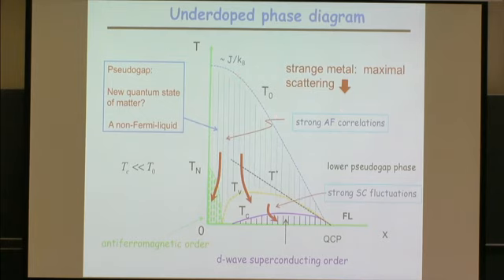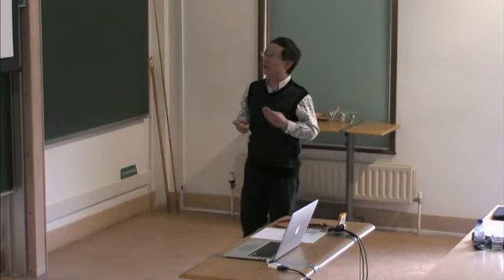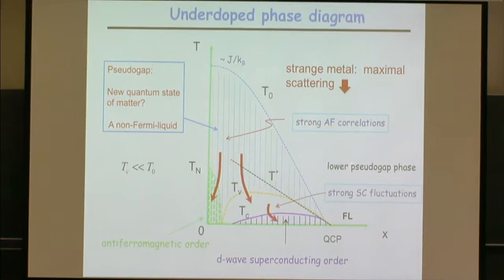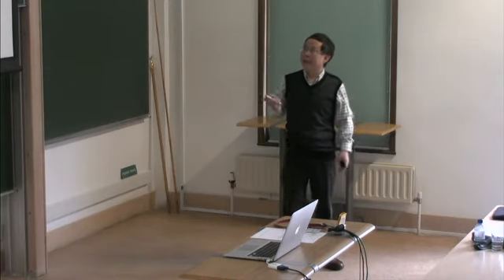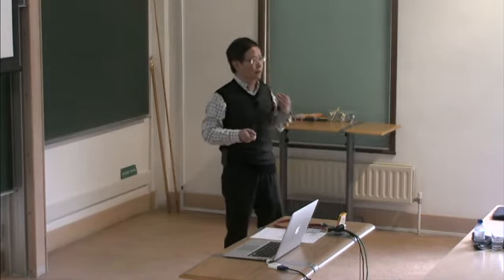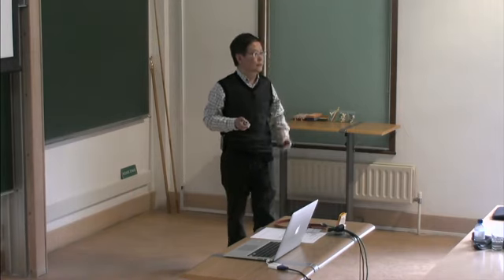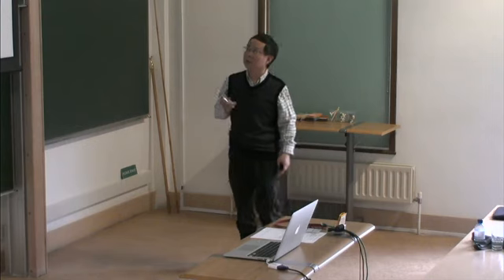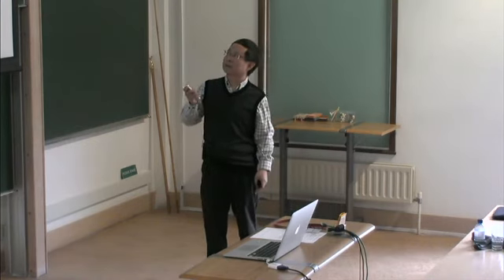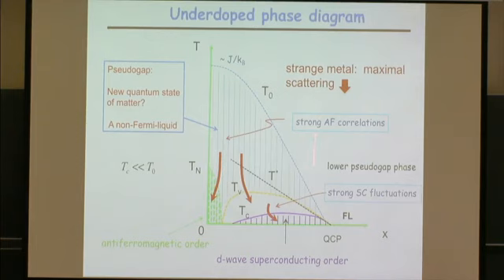Actually, beyond this regime, you will also see very anomalous behavior, which is not like a Fermi liquid at all. And there is actually the strongest possible scattering of the electrons. Many people in this workshop will talk about the so-called non-Fermi liquid behavior in this regime. Only in the overdoped regime, at low temperature, is there an indication that the Fermi liquid possibly gets recovered.